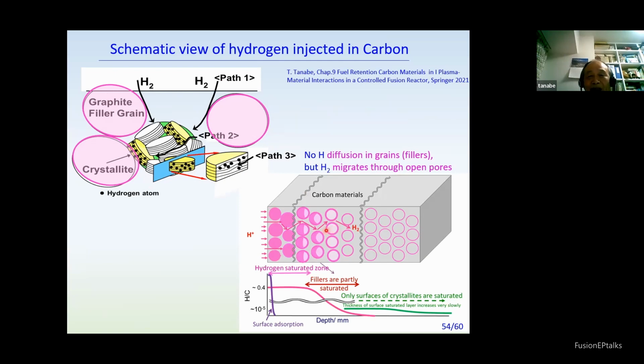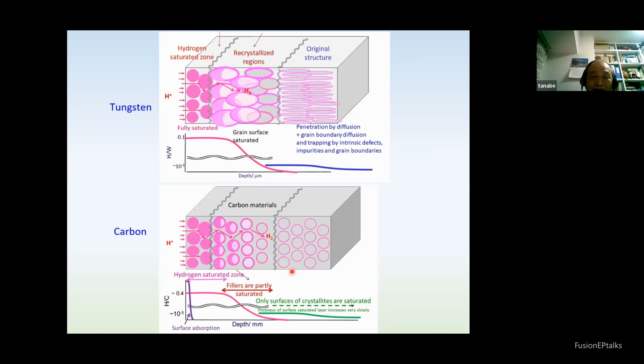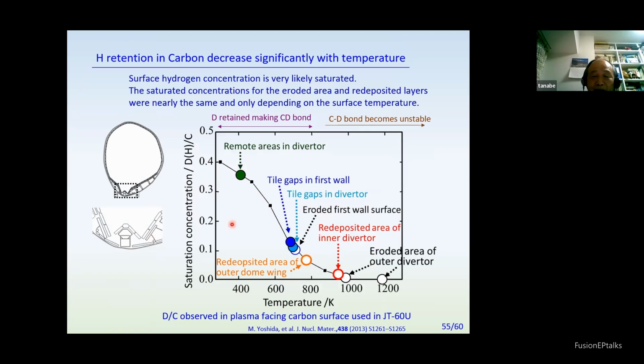But hydrogen molecules, because they have open spaces and open pores, penetrate this way, and hydrogen concentration becomes very high at the surface and saturated, then only the near-surface of the fillers becomes saturated and decreases this way. So the difference is given here: particularly large diffusion versus no diffusion, but high saturation concentration. This is a typical difference. Retention in carbon significantly decreases with temperature - this is the observed result.